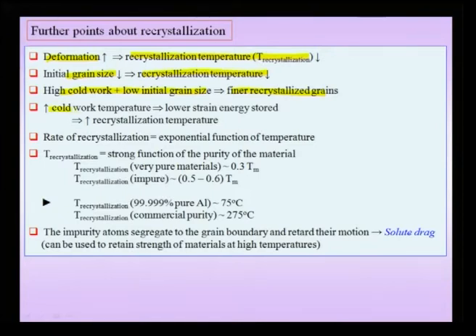And if the cold work temperature increases, then a lower amount of strain energy is stored in the material, because, as I pointed out, some of these processes, like recovery, can take place while deformation is in progress, and therefore my recrystallization temperature increases because less energy is stored. The rate of recrystallization is an exponential function of temperature. This is something like the Arrhenius behavior, but we have to note that at the heart of recrystallization there is not one single process but multiple complex processes. Therefore, the activation energy which you calculate using this Arrhenius kind of function is not for a single process but for a complex set of processes.